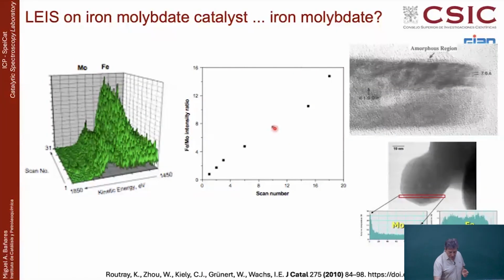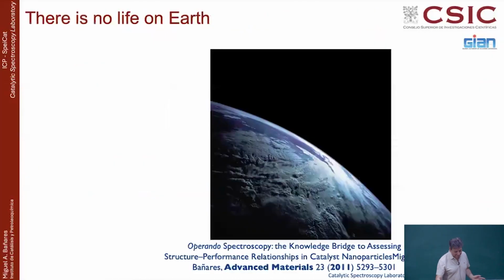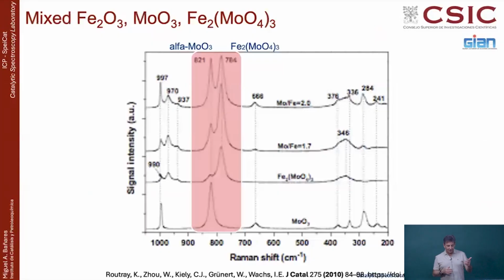And even when you make element profiles, you can see that there is a maximum of concentration of molybdenum at the edges of the particles compared to the middle. And of course, as you go there, you see that the iron has minima at the edges because you have a surface enrichment of molybdenum. So the surface, what the molecules see, where the reaction happens, is mainly molybdenum. Again, surface and bulk, so keep that in mind.